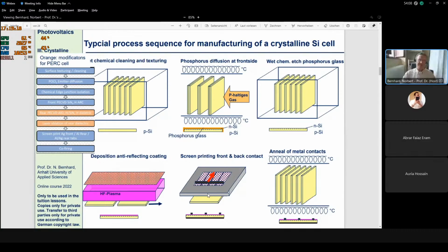That means after this deposition of the passivation layer of the front side, you see this is front PECVD silicon nitride, we have to deposit this double layer of aluminum oxide and silicon nitride at the back side. And in the next step, of course, we must interrupt this layer at certain points just to be able to make the back contact. And this is done by a laser ablation process of the rear dielectric. That means at certain positions, we just remove then the deposited double layer of aluminum oxide and silicon nitride again here at the back side, and afterwards we print again, as in the previous step, also on the back side, the aluminum layer.